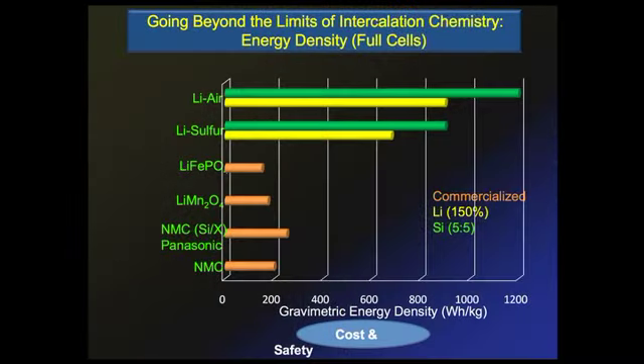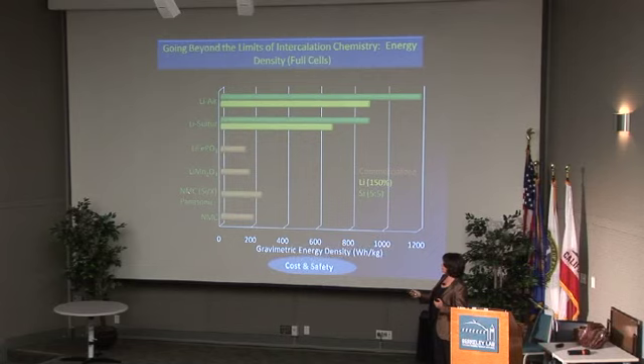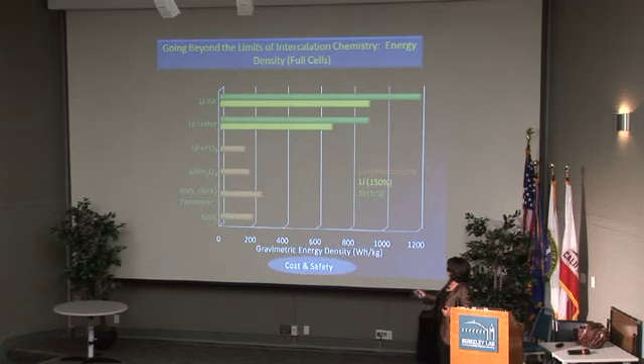So if we want to think about going beyond the limits of intercalation chemistry to higher energy cells, what is beyond there? This is the NMC material, nickel manganese cobalt oxide, one of those layered oxides I described. This is all gravimetric energy density. This is the same material coupled to a silicon negative electrode. This is the spinel, which is used in the Chevy Volt. This is lithium iron phosphate, which has actually made its way into the BYD car. And you can see there are respectable but not high enough gravimetric energy densities for these materials.